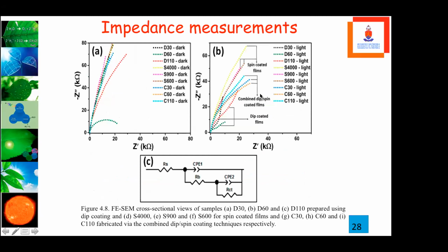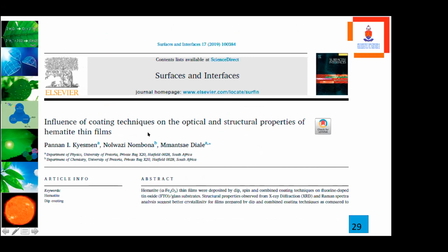Another experiment is that we have established in our lab electrochemical impedance spectroscopy, where we are able to do impedance spectroscopy measurements for the hematite in water or in an aqueous solution. And we are able to produce very nice results that you can see here for dark measurements and for the light measurements using either a combined coating or dip coated methods. Many of the people out there are still using only dip coating methods, and we have published this paper on influence of coating techniques on the optical properties and structural properties of hematite thin films.